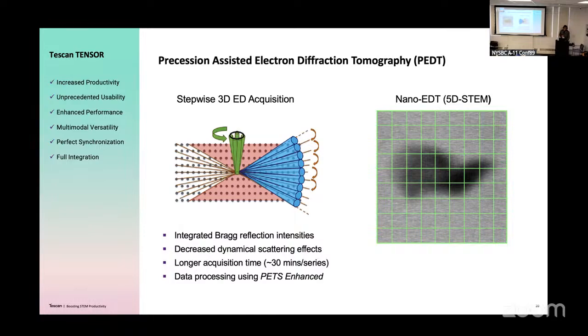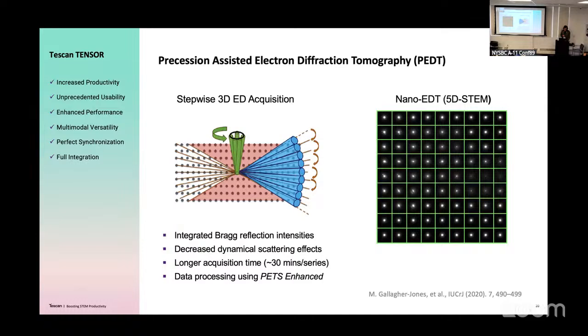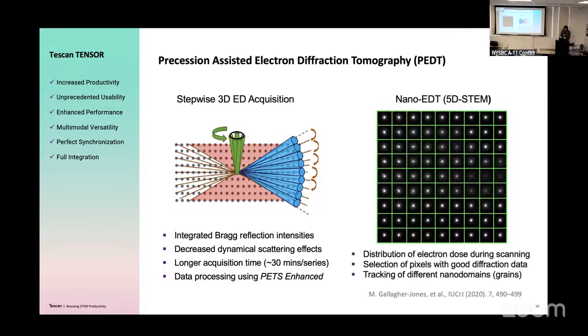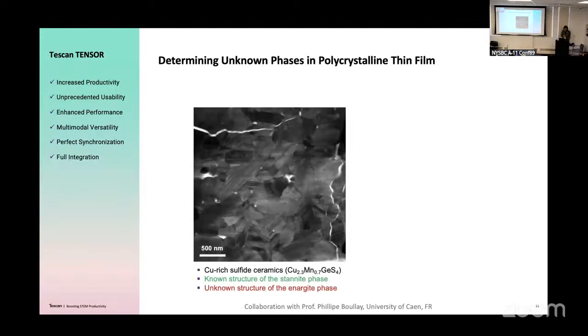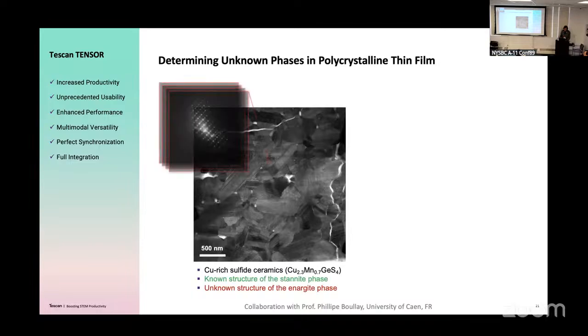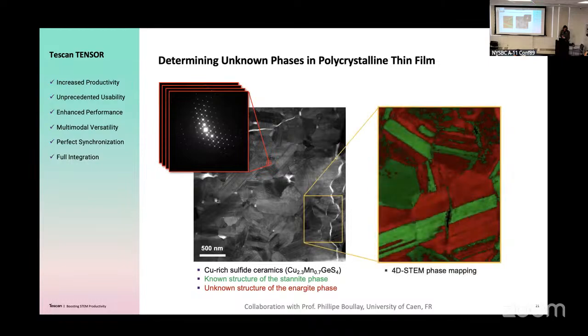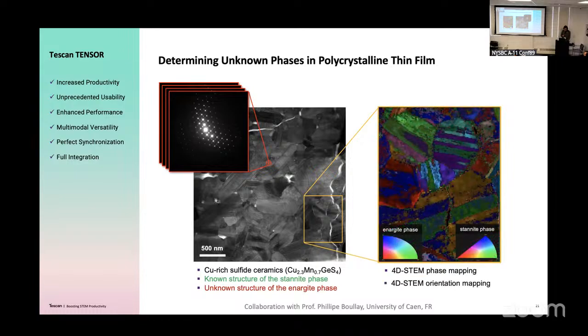So now here you can do a 5-dimensional scan, basically rastering your sample, and at each position you take such a 3D precession map. You can use this then for full characterization of your sample. So you distribute the electron dose optimally on your sample. You can use only those areas which diffract properly and contribute, and you can track nanodomains. In that case, they use this to determine unknown phases and their orientation. This is illustrated here. So you have the 4D-STEM phase map, and I agree 4D-STEM will be the future. So you have the phase map, and you also get the orientation of the unknown phases. Yeah. So this is working really neatly.